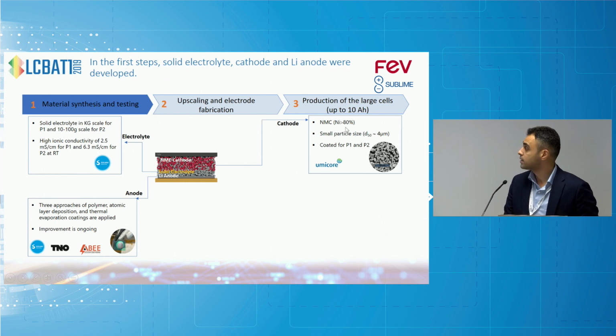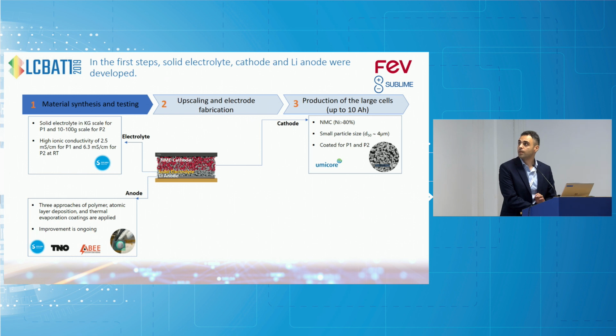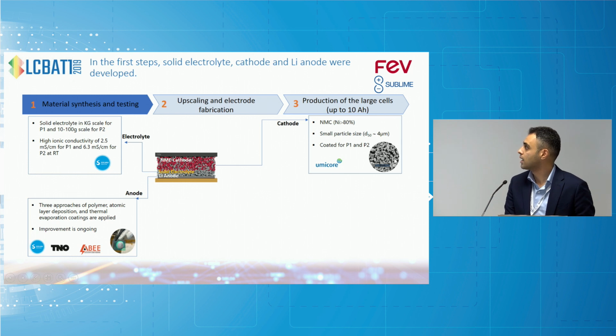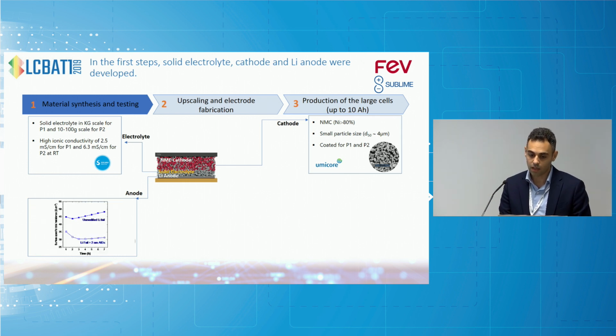For the cathode, a special NMC cathode is developed for both pathways by Umicore, with small particle sizes and special types of coating that allow us to gain high capacities at high C rates. For example, at 1 C we can get a capacity of 180 to 190 milliampere hour per gram with this special type of coating.